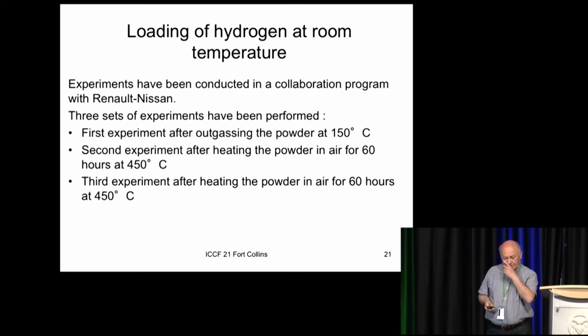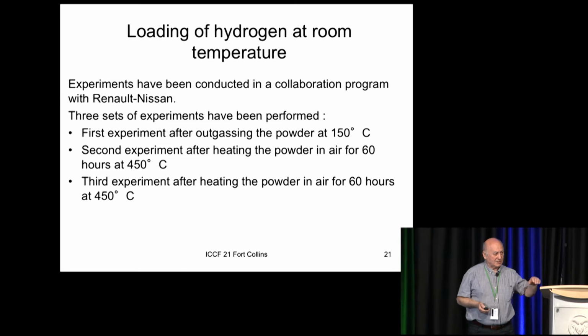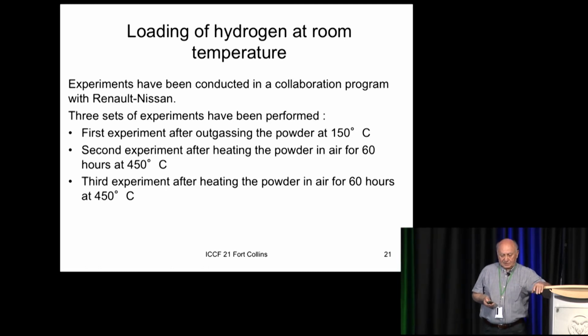So experiments have been conducted in collaboration with a program with Renault and Nissan. As you know, Nissan is working with a number of Japanese universities. And I had a chance to develop this technology using their powder. It's not my powder. So I'm using the same zirconium, palladium, nickel powder. And the first experiment was done outgassing the powder first at 150 degrees to remove the vapor, the moisture, and then putting the hydrogen and heating the temperature.